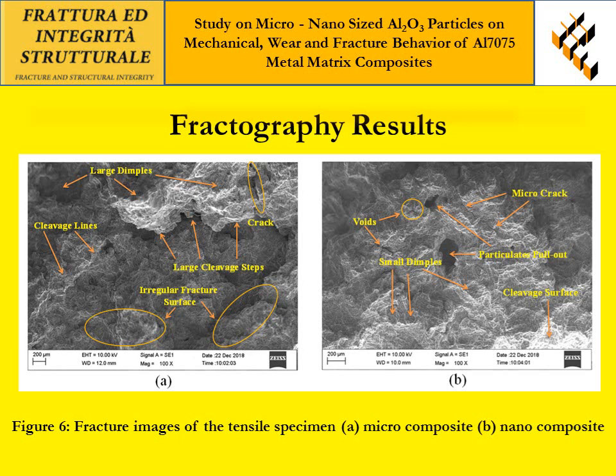Figures 6a and 6b show the tensile fracture surface for the micro and nano composites. The fractured surface of the test samples indicates distributed shallow portions and dimples of different sizes within the MMCs. This also confirms the high ductility witnessed in the tensile test studies.